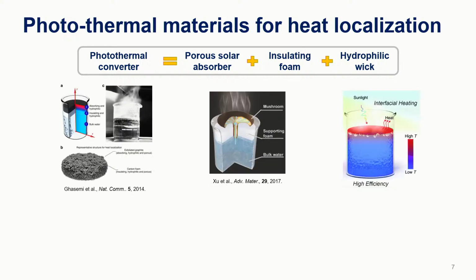And so there have been several prototypes of this, mainly using carbon-based foams. So here you're seeing a carbon foam, which is porous, and so it has a very high solar absorptivity. And because it's a foam layer, it has a low thermal conductivity. And finally, we can use a wick to deliver the water to that surface. And so what you end up getting is you can even generate steam under just natural unconcentrated sunlight, because you're keeping all the heat at the surface and not losing it to the bulk.